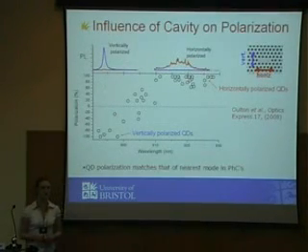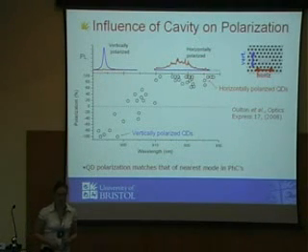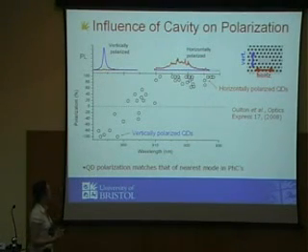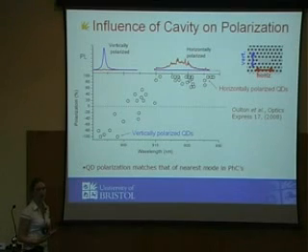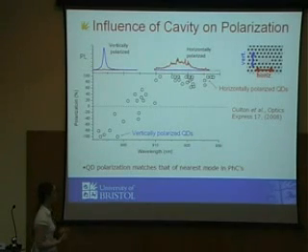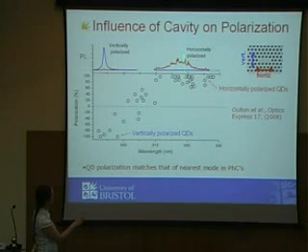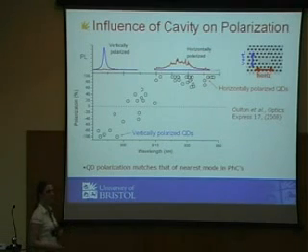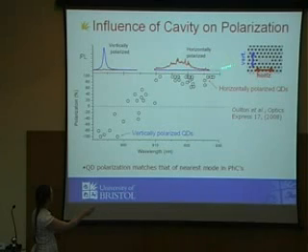So what happens to the quantum dots then if you put these in the cavity? Well, what we did with this structure was simply lower the excitation power that we're looking at, and that means that we can make out the sharp individual lines coming from each quantum dot. You can see here this is some indication of these kind of sharp features here, but you lower the power and you see them much more clearly. What we did then is measure the polarization of each of these quantum dots as a function of where they were spectrally, where these modes are here.